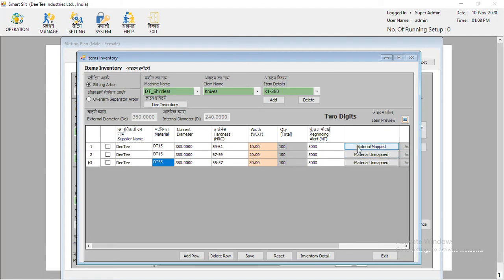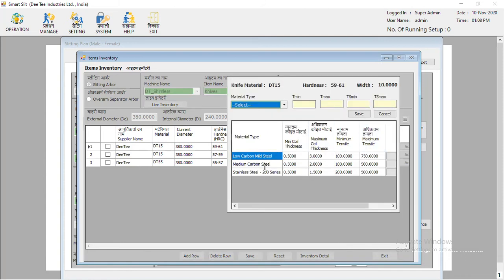Just to show you an example, I have done a mapping for a single material. So 10 mm thickness I have mapped like this. With this particular knife of DT15 material, 59 to 61 HRC, thickness 10 mm, for low carbon steel, minimum coil thickness I can use is 0.5 and maximum coil thickness I can use is 3 mm. Minimum tensile strength I can use is 100 megapascal, MPa, and maximum tensile strength I can use is 750. This is what the knife manufacturer has suggested.